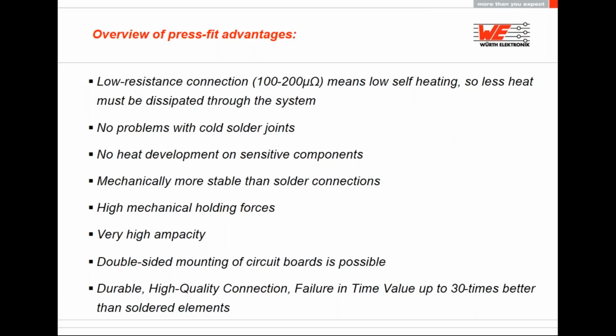So let's talk about the advantages of the press fit technology actually. So first of all, it's a low resistance connection, which is around 100 to 200 microohms, which means low self-heating, and so less heat must be dissipated through the system. So low heat will go to the rest of the PCB, very low heat, and less heat dissipation will be needed. So right away, this is a great advantage for this technology.